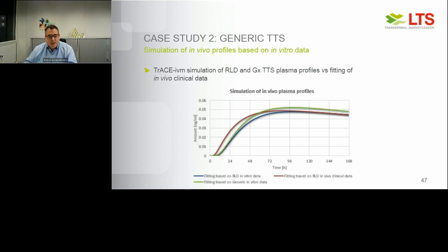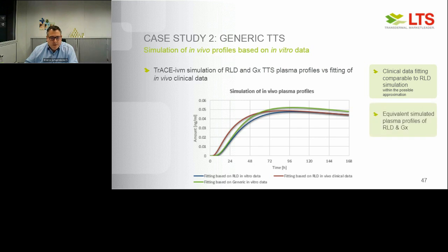And we now add the data based on our in vitro data set for the generic patch formulation. We see it's pretty close to the blue curve. So the clinical data fitting of the RLD is within the possible approximation, and the data set we're using here, which can also be different in the clinical setting, is pretty close. But especially when we compare the profiles between the reference listed drug and the generic formulation in green, they are quite equivalent within a reasonable error. It's a good simulation to show that we can support decisions on whether we go to another BE study with these prototypes or not. So we have now seen two different applications of our TRACE IVM tools to justify going to further steps in development or not.